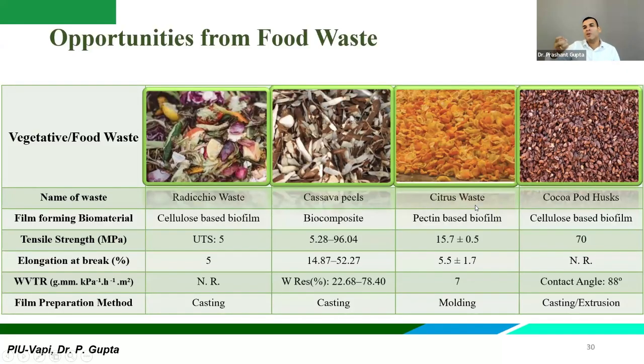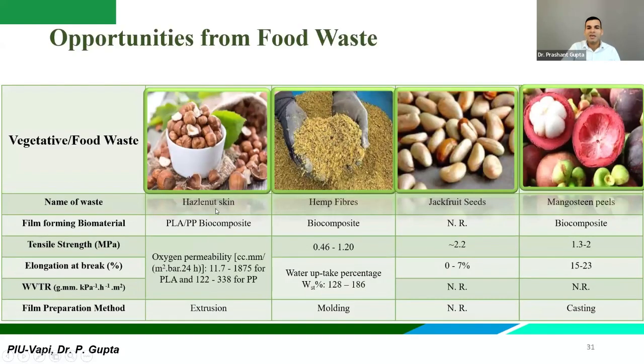Citrus waste, let's say orange juice is extracted and the fiber based materials are left away, right? So it can create a pectin based biofilm. When you look at the strength, let's say 15 megapascal. If you look at LLDPE, it will give you maybe 16 to 17 megapascal only. And if you can engineer and tailor this product, you can certainly get a good value. Then cocoa pod husks are there. Again, you get cellulose-based nanofilms. Now these are hard, and that is why the material has very good tensile strength. You can utilize casting or extrusion. You can utilize compression molding for citrus waste. Hazelnut skin is there.